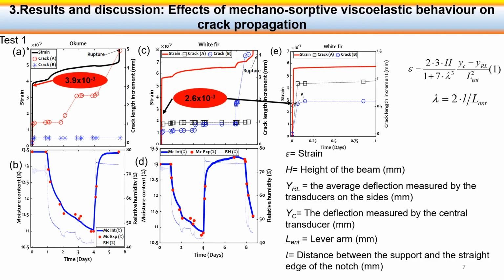We present the strain due to the mechanosorptive and viscoelastic behavior effect on the crack propagation of the test beams until the rupture of the test one, and the evolution of moisture content. From this curve, we can see that the instantaneous strain of Okume is greater than those of white fir. We zoom in on figure E of white fir test 1. During the instantaneous loading, to better see the timing of the loading, as shown by the circle area P1. The crack propagation tends to develop on one side of the beam while it remains almost constant on the opposite side. This is the case in Fig A and Fig C.